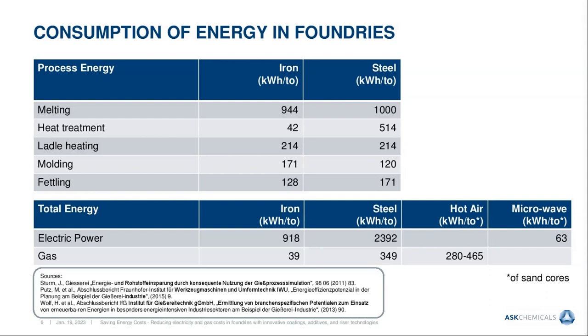What is the consumption of the energy in the foundries? Certainly, the melting takes the majority of the energy. In iron and steel foundries, it's about 1,000 kilowatt hours per ton of molten metal. And in steel foundries, we have a big chunk of energy for the heat treatment, which is about 500 kilowatt hours per ton. Furthermore, we have ladle heating, molding, fettling, etc.